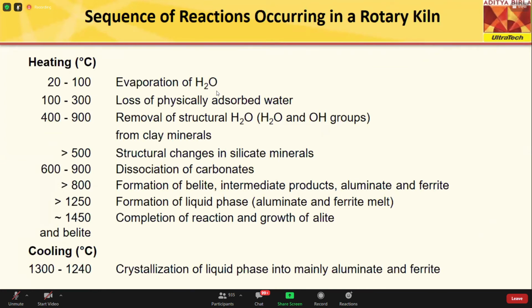Before explaining that slide, we'll see the process of formation of clinker at different stages. So initially, the raw mix is at 50-55 degrees Celsius, which on heating, the available moisture gets evaporated. Then at around 100 to 300 degrees Celsius, physically adsorbed water escapes out, and as seen in the slide, at 400 to 900 degrees Celsius, the structural water from clay as well as other argillaceous material get out of the system. Then at around or more than 500 degrees Celsius, structural changes in silicate minerals are observed. From 600 to 900 degrees Celsius, dissociation of carbonates, that is the calcium carbonate limestone, gets calcined and CO2 gas escapes out of it.